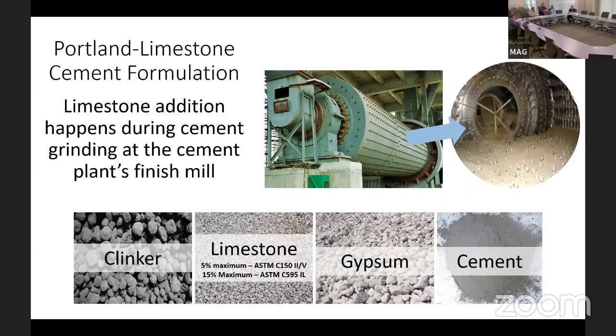So this lime is getting molten, combining with the other oxides that are inside the kiln, and you're getting the target properties that you need for cement chemistry: tricalcium aluminates, tricalcium silicates. This is what gives you the properties to have a hydraulic cement, something that's going to react and hydrate when you introduce water to it to begin the stiffening, hardening process of concrete.